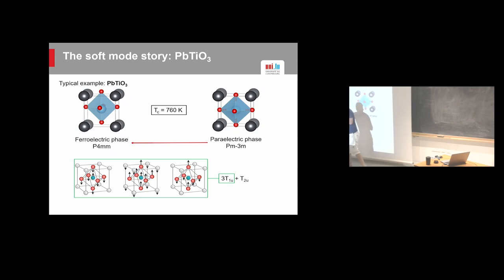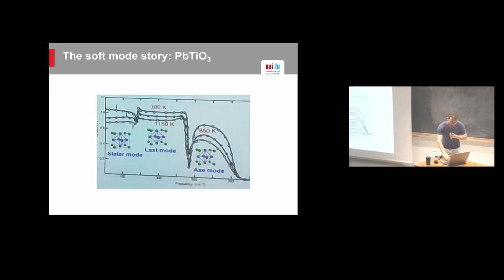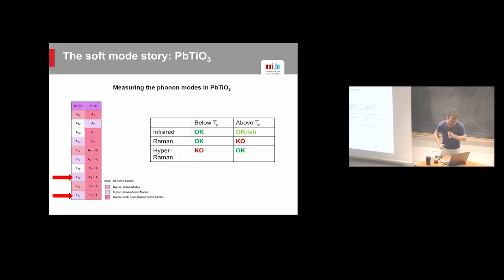So sometimes you might have mixing between those 2 modes, and especially when you vary pressure or you vary temperature, you might have also a gradual change in the actual atomic displacements that are associated to the phonon. So this should be really seen not as something intangible and fixed by symmetry, but only as a basis on which you can analyze your atomic displacements. Okay, so this you've seen.